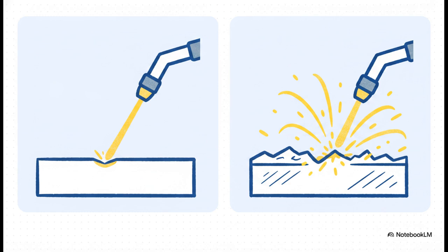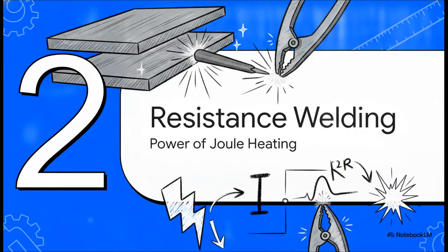They can actually use different electrical polarities depending on what they're joining. For standard steel, direct current electrode negative, or straight polarity, is the go-to. The electrode tip is usually a sharp point, focusing all that intense heat right on melting the base metal. But aluminum is a totally different beast. It has this really stubborn, tenacious oxide surface layer that straight polarity just can't punch through. So, by switching to alternating current, the rapidly fluctuating polarity basically shatters that oxide layer, giving you a beautiful, clean weld.